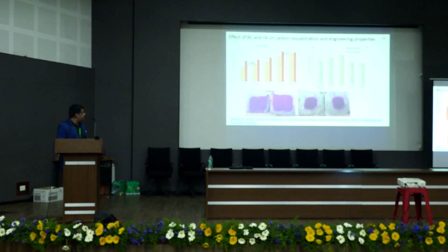So with that in mind, we tried out fly ash as a possible option, which is one of the most common cement replacing materials. We replaced 20% with fly ash, and we combined that with biochar as well. And we found that the net CO2 uptake actually goes up when we have biochar in the system, and when you also have a combination of fly ash and biochar in the system. And after this, we measured the strength at 7 days and 28 days, and we see that the strength improvement is also very evident, which is of the order of 15 to 20% compared to control.